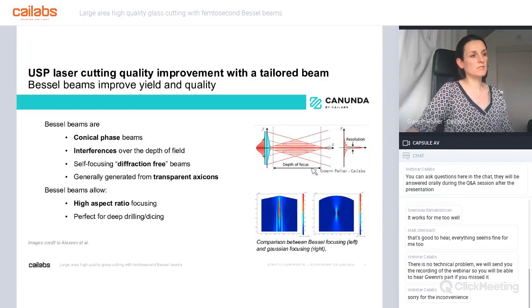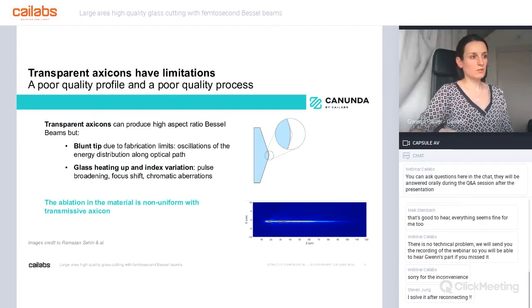So basically here you have a transmissive AXICON. You have the beam coming in on this side and coming out of the AXICON through this conical plane. So the beam will have a conical phase, and when both beams meet, they will interfere, and this interference will actually create this very intense and very long beam. So you have to imagine, of course, that all this is in 3 dimensions. So these AXICONs are the best way to generate this really high aspect ratio, and they are perfect for drilling through glass. But the thing is that this classical way of generating Bessel beams with transmissive AXICON has limitations.